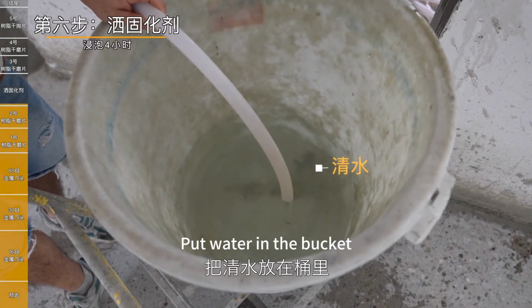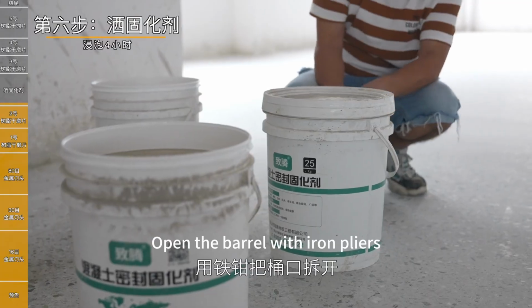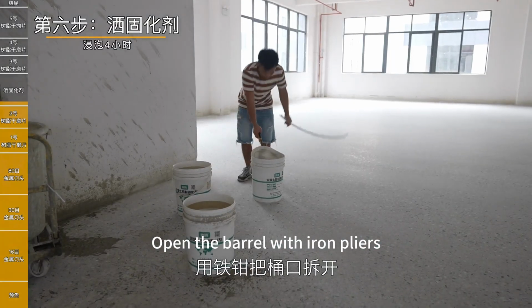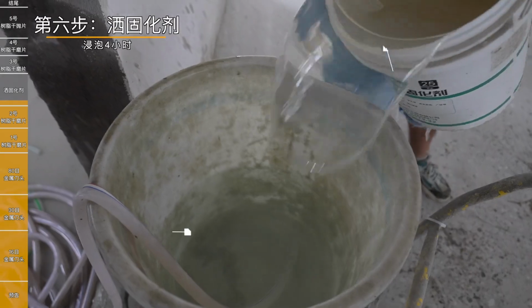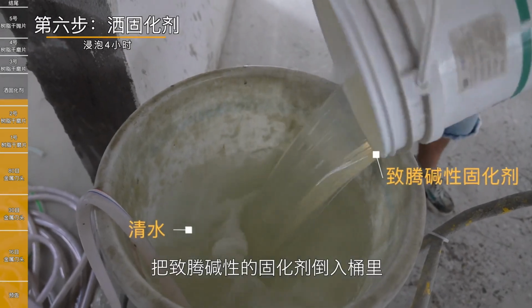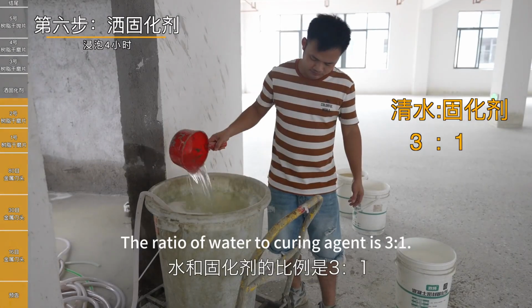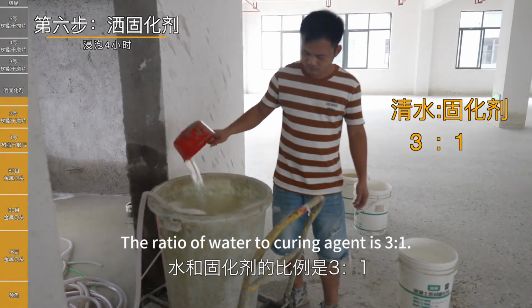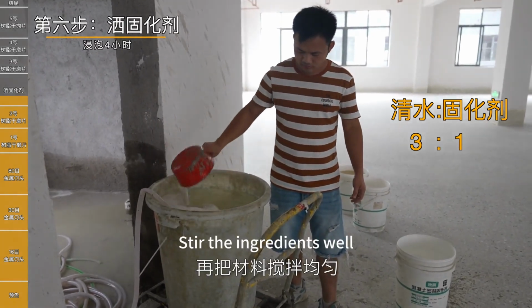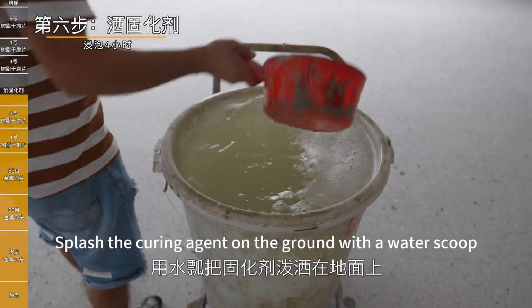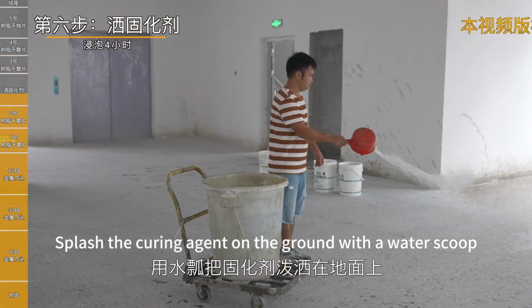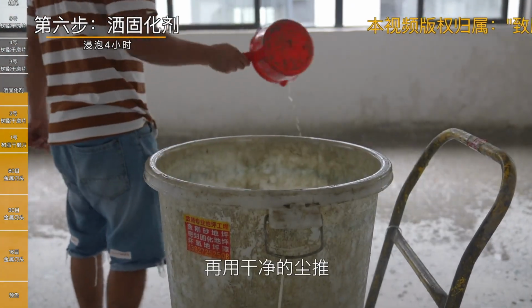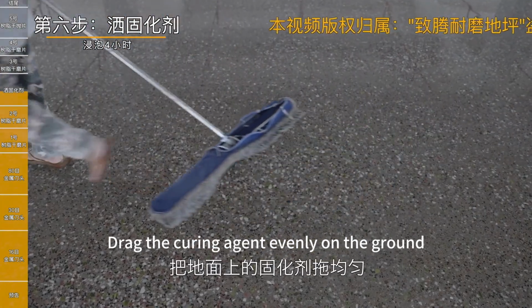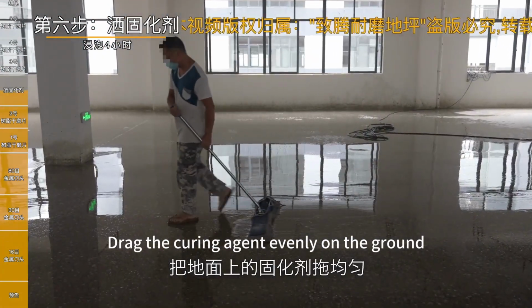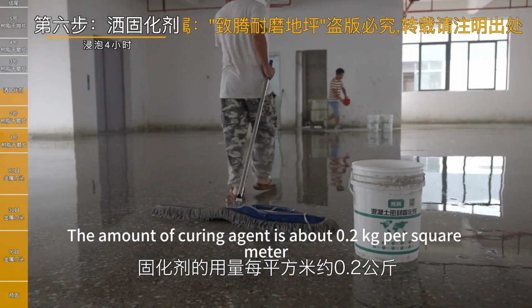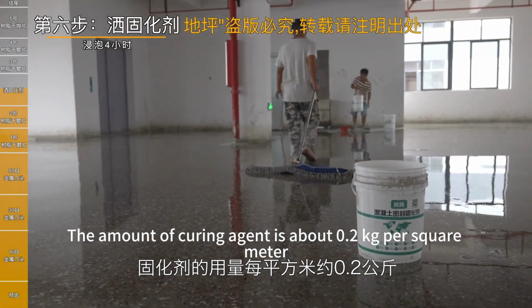Put water in the bucket. Open the barrel with iron pliers. The ratio of water to curing agent is 3:1. Stir the ingredients well. Splash the curing agent on the ground with a water scoop. Push it with a clean dust pusher. Drag the curing agent evenly on the ground. The amount of curing agent is about 0.2 kilograms per square meter.